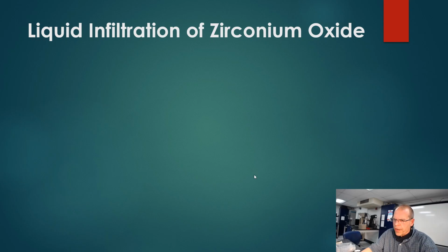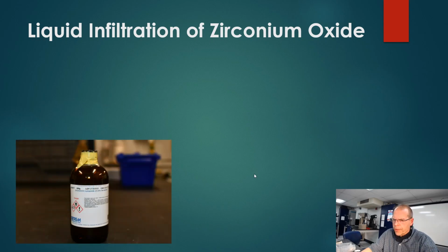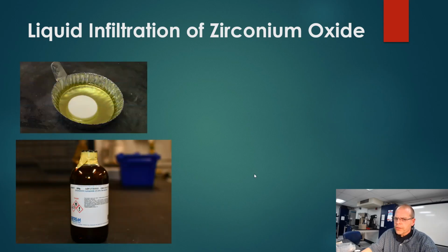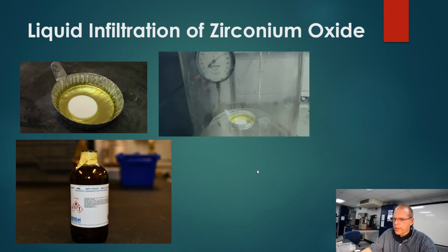So with the liquid infiltration part of this, again, there's our precursor. We are going to soak our disc, again, our green body, about halfway in this solution. Okay, so again, half in, half out. I've tried different mechanisms in doing this. We've let it sit for 30 minutes and just through capillary action, pull it in, hopefully in all the pores. I've actually tried using a vacuum bell jar where we actually suck some of the air out of the discs and hopefully pull this in at a quicker rate.